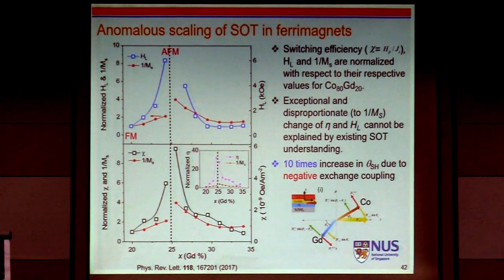By changing the gadolinium composition, 20% gadolinium is very close to still ferromagnetic-dominated, like a pure cobalt. 25% gadolinium is almost perfectly compensated, like antiferromagnetic-like. So we can measure those all the way. And then we found the spin orbit torque efficiency increases about 10 times once you go close to this antiferromagnetic coupled